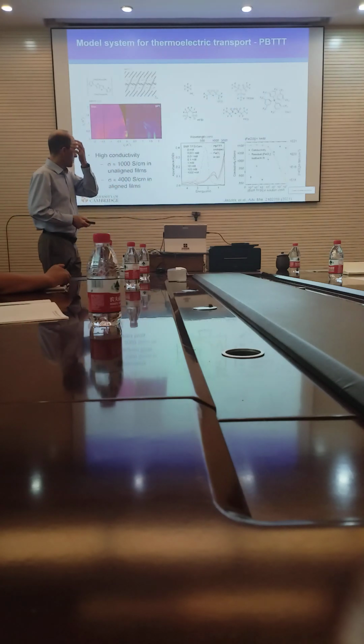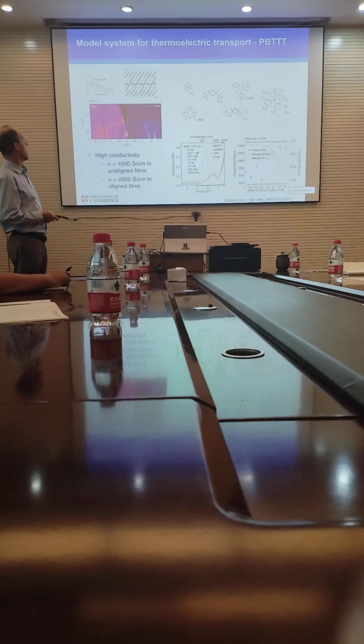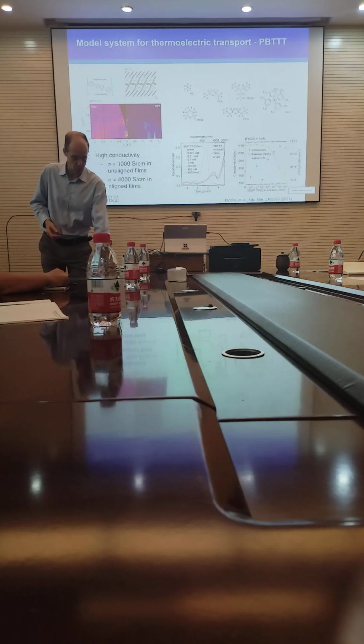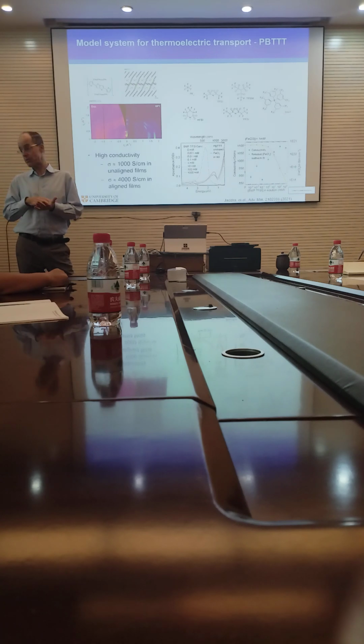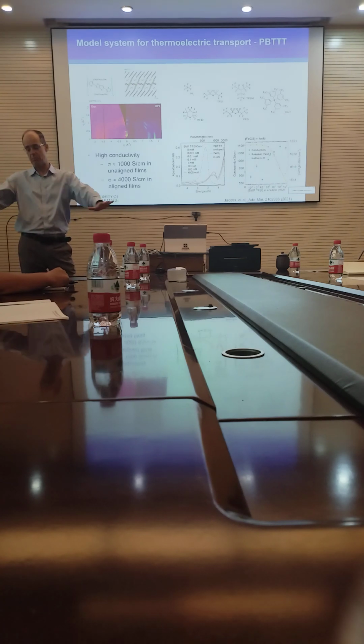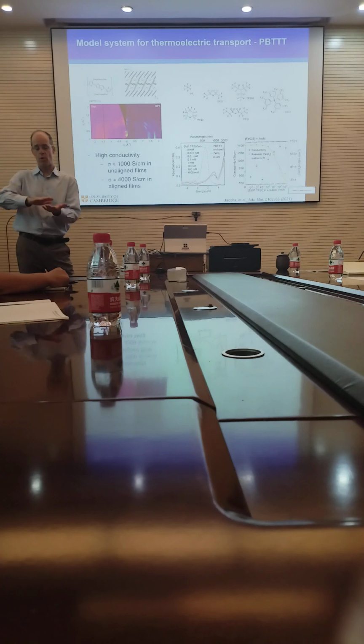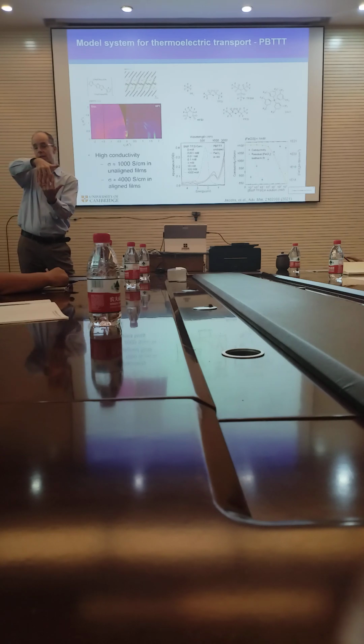So one of the model systems that we've looked at in a lot of detail is PBTTT, this thiophene-based conjugated polymer doped with these different ionic liquid anions. So you can see here the microstructure of PBTTT. PBTTT, as many of you will know, forms this lamellar microstructure, where essentially parallel to the substrate, you have an alternating layer sequence of conjugated backbones and alkyl side chains. The alkyl side chains interdigitate. So the undoped system is a beautiful crystalline system with interdigitated side chains.